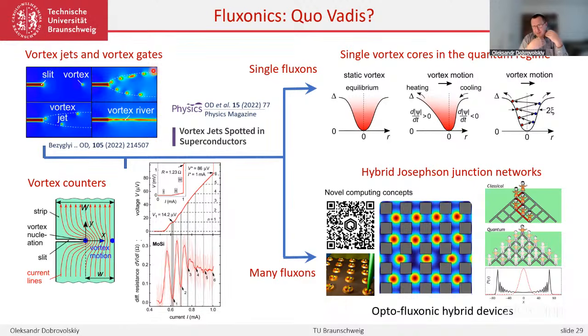If we continue to increase the driving current, then the time of flight will be shorter. The perpendicular component of the velocity will be higher and higher, and vortices will not have enough time to open the divergent angle for the vortex jet. So they will be sticking together, and electrons escaping from the vortex cores will lead to their attraction. These two opening vortex rows will stick together and form one single vortex river. A vortex river is a dynamically formed Josephson junction, where the order parameter is only slightly modulated. So vortices, like Josephson vortices, are moving very fast.